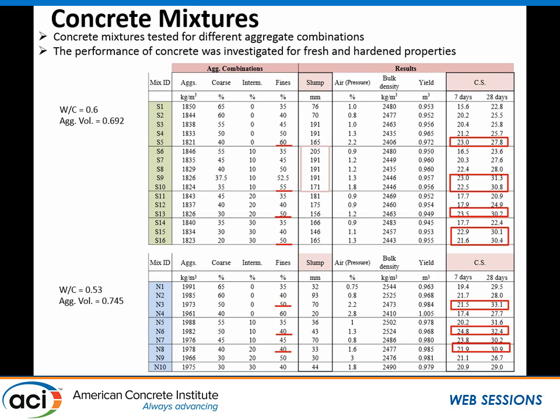This is comparing these to practical mixtures they use in the field, such as 60-40, 60 coarse, 40 fine, that get 25, you can go up to 31. You get 7 MPa more compressive strength, where you're talking about a low cement content mixture that is 20 to 30 MPa at 28 days. Well, there are no admixtures in these mixtures, and these are all plain. That's why you see these high slumps over there.